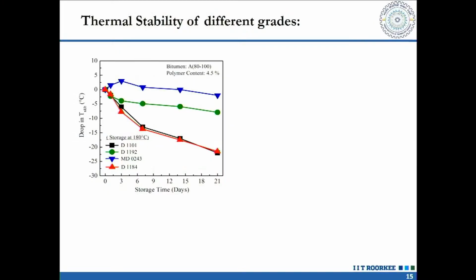So all of us are aware that the bitumen, during manufacturing, during storage, during construction, during use in the road, is subject to high temperature and high moisture content. So the aging of the PMB becomes the most critical parameter. Initially it can have good properties, but what will happen after 1 year, 2 years of use? So here the data clearly says that the linear and the radial, which is the black and the red data, clearly show that during usage or during storage, their properties gradually erode. But the same erosion in the properties is not observed in the case of high vinyl content SBS polymers. So what is the trick?